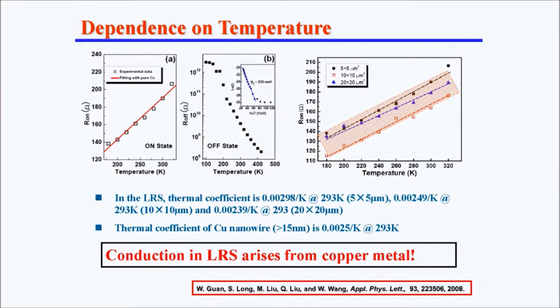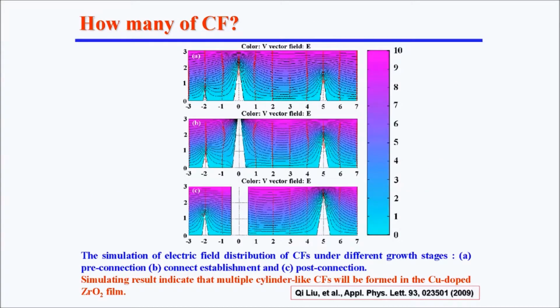So then we do temperature dependent measurements. For each different size device, we extract their thermal coefficients. They are almost the same. Also, if you compare this thermal coefficient with copper nanowires, they're almost the same. So we deduce that maybe this conductive filament is consistent with copper. Then we try to answer whether it really can form multiple filaments.